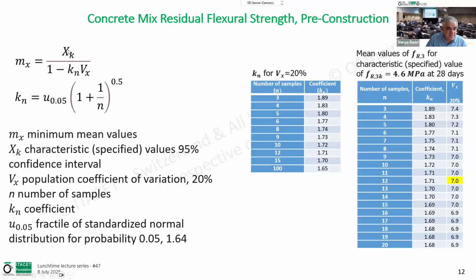This is the specified value we have. This Kn is a coefficient depending on the number of the tests. For example, here we are using 12, so the Kn is 1.71. And Vx is a coefficient of variation, which usually at the beginning we use 20%. So you see here, based on these numbers, for a 4.6 FR3, our average mix result should be 7. So this is how we design the mix.